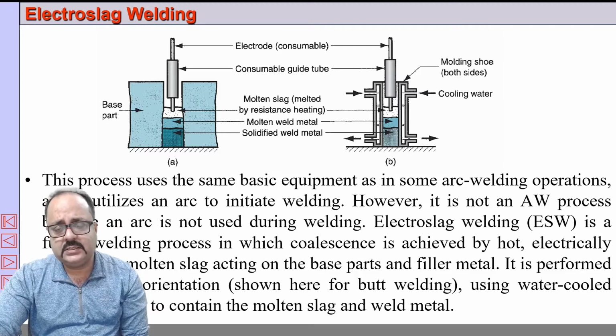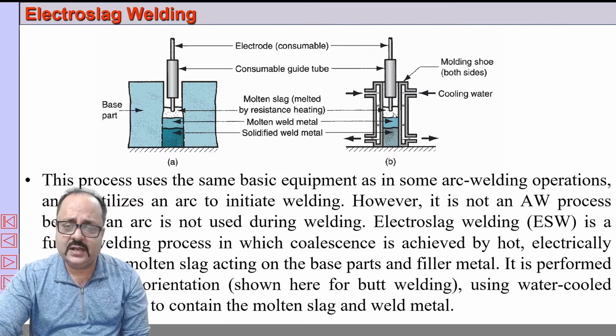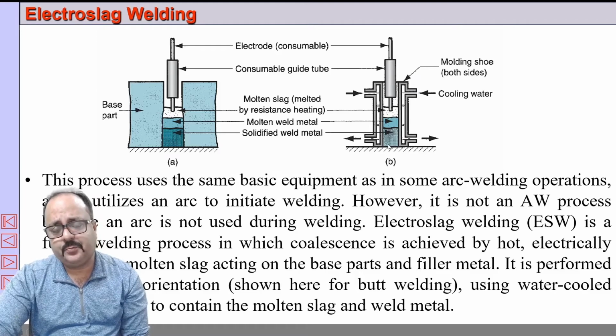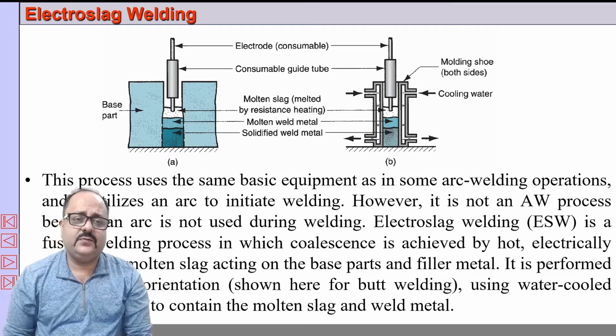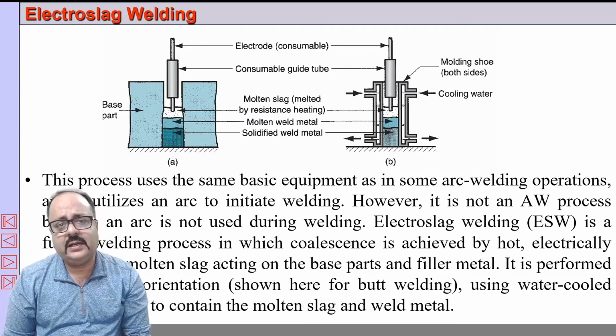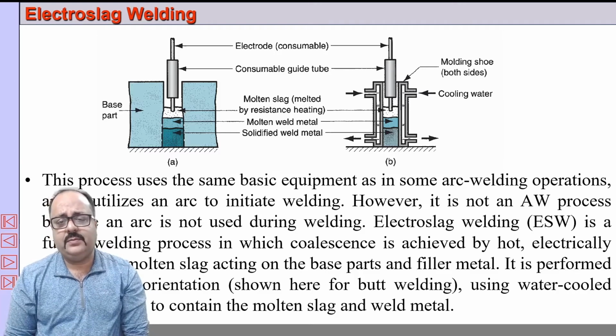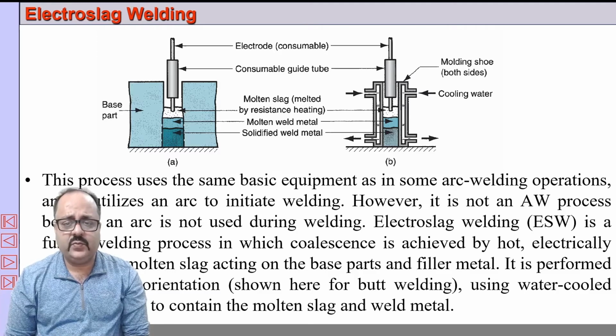And the arc produces a slag. This slag then engulfs the arc, and there is a short circuit between the slag, which is light, floats and touches the electrode. Once it touches the electrode, the arc extinguishes, but however this slag that is produced is conducting in nature. Since this slag is conducting, electric current is passed, and because of resistance heating, the metal pieces will be melted, the electrode will be melted, and the tube guide will also be melted and deposited in such a way as to form a joint between the two metal pieces which were being joined. So this is the basic fundamentals of electroslag welding.